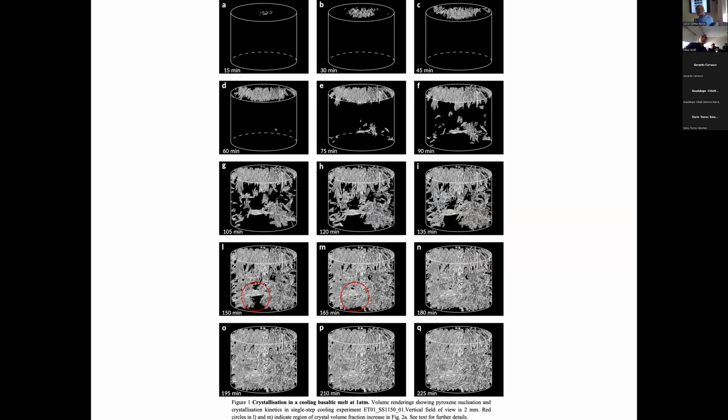Okay. Then we have heterogeneous nucleation from the crucible. So the contact between the melt and the alumina crucible, because the crucible also reduces the surface energy. And just after 150 minutes, we observe, at least what we can understand, a homogeneous nucleation in the middle of the sample.